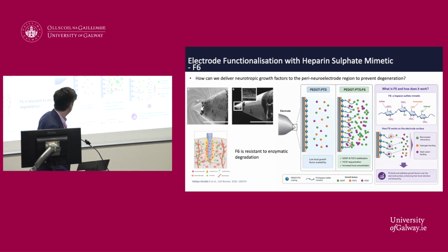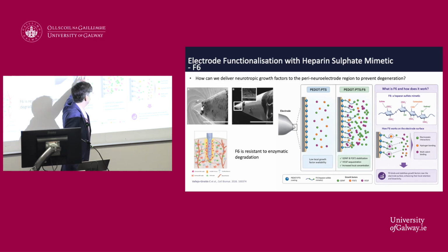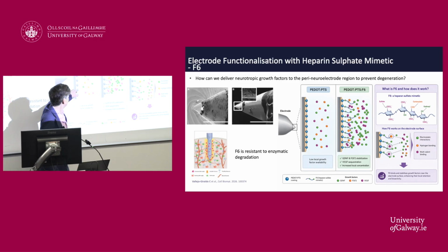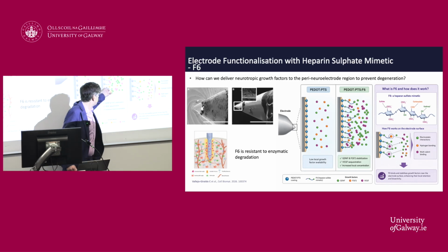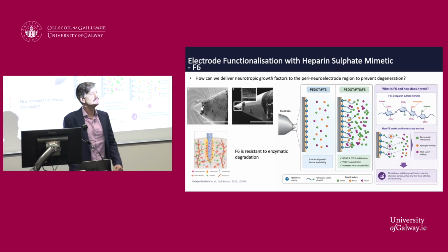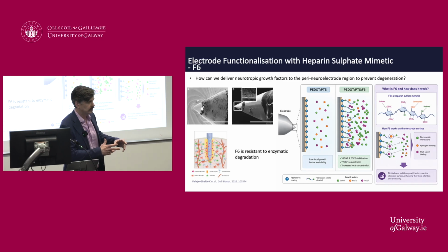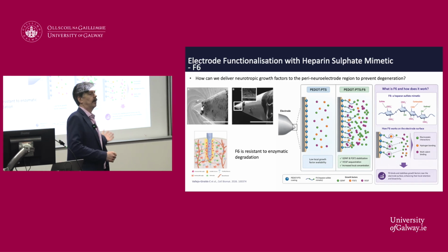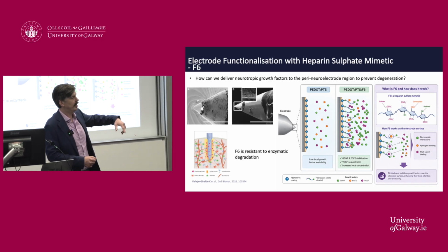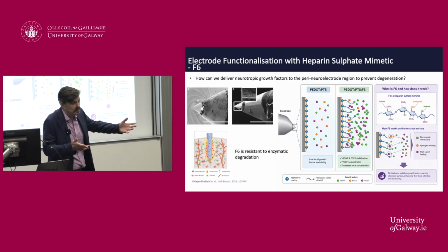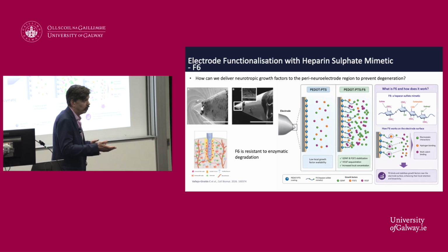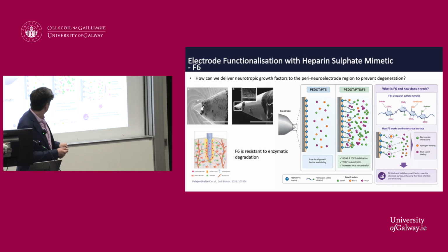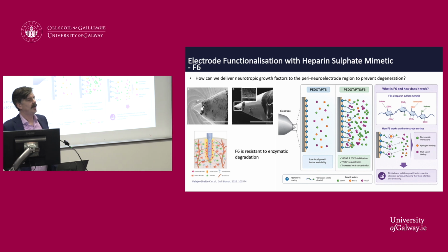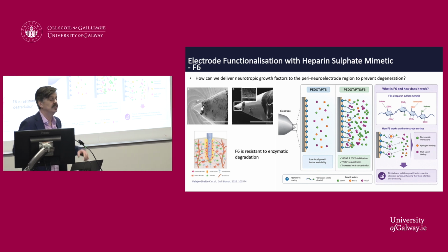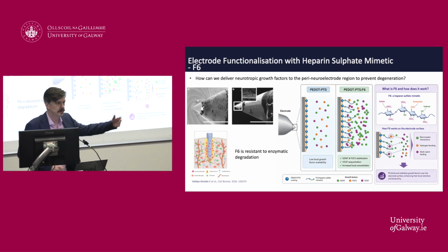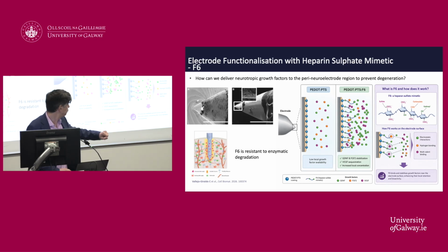So in effect, what do we have? A conductive biochemistry that we coat the surface of our electrode with, and this will present heparin sulfate. The heparin sulfate will bind endogenous growth factors. So we're not relying on supplying growth factors by coating our electrode in growth factors, which has been looked at for a long time. It doesn't work very well. We instead coat our electrode with a sequestering chemistry that will bind endogenous growth factors and present them to the neurons. Okay?